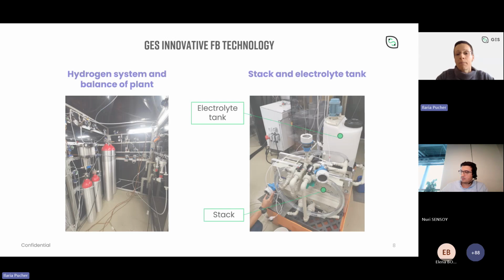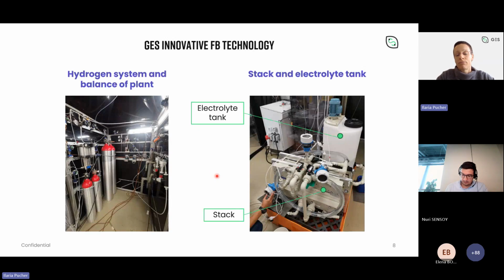So where are we now? Here is today's situation, more or less. So we are testing stacks on the right-hand side. At the bottom, you can see one of the stacks that we are testing right now. The electrolyte is stored in the tank that you can see here at the top. While on the left-hand side, you can see the hydrogen system part with the balance of plant. We are actually going to test a stack that is 4 times the power of this stack in about a month. And based on the size of that stack, we created some realistic rendering of how the final power module will look like.